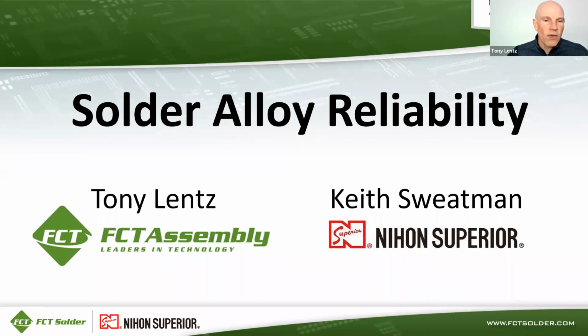cross-sectional pictures. And so the solid solution strengthening, because the elements are fully dissolved in the tin matrix, they stay dissolved over the life of that test and they don't change. And so they maintain their strengthening effect throughout thermal aging and thermal cycle testing. Whereas particles that are precipitated out tend to agglomerate and collect together and become larger, and they lose their effectiveness. They no longer provide the strength that they once did when it was small, finely dispersed particles.